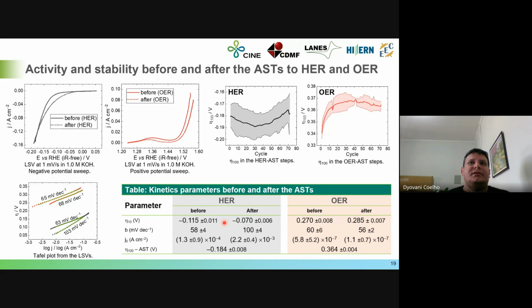So after the accelerated stress test, there is a huge decrease of the overpotential to reach 10 milliampere per centimeter squared for hydrogen evolution reaction, but it happens just at low current density, not at higher current density. At higher current density, we have other effects like transport limitations, the bubbles on the surface and things like that, which just make the analysis really hard.